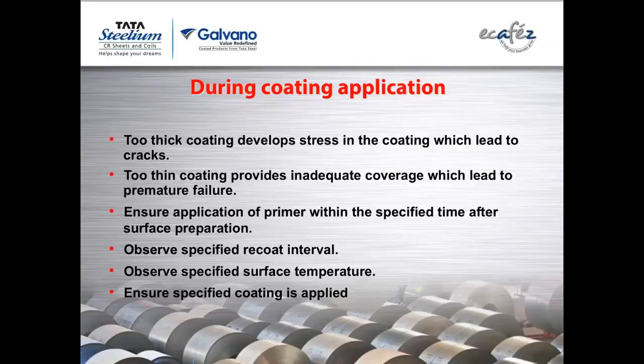During coating application, you need to understand few things. Too thick coating develops stress in the coating which leads to cracks. There's something called as mud cracking, what we say, especially in case of inorganic zinc silicates, you'll find it. Most of the other coatings also you'll find it. With inorganic zinc silicate, they are very pronounced. But in certain other coatings, it might be hair cracks or something, which probably you will not see by bare eyes. Too thin coating provides inadequate coverage, which leads to premature failure because there is not enough corrosion protection.